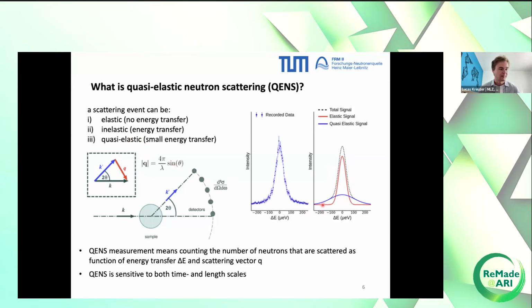And now one more detail, and then I'm done with the theory part of this technique. With QENS, we detect foremost the incoherent scattering, and hydrogen is an element that has an incredibly high incoherent scattering cross-section. So whenever you have hydrogen in your sample, your signal would be dominated by the scattering signal coming from the hydrogen. Hydrogen is also in water, and we are interested in this water. So if you set the QENS instrument to a suited energy range where you would detect movements of hydrogen, then you would detect only the movement of hydrogen that sits in water molecules. So then you can really follow along the movements of water.